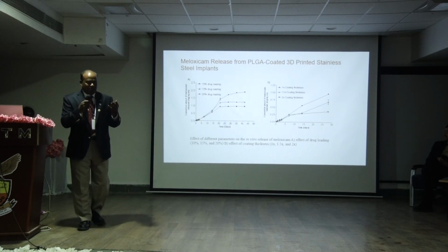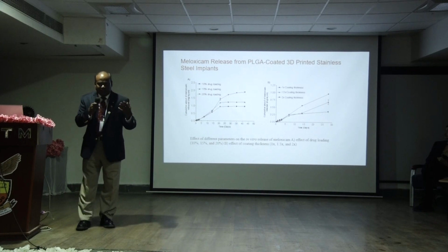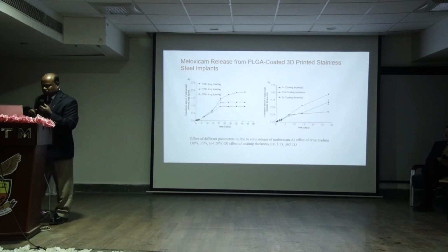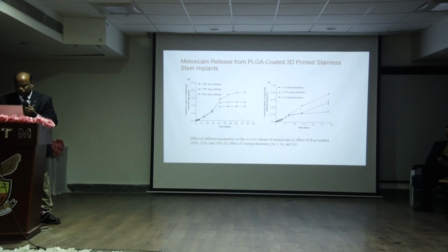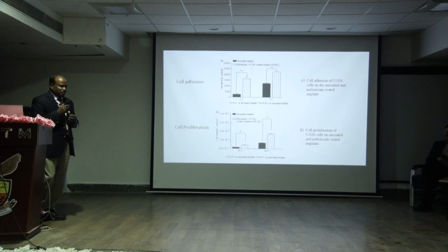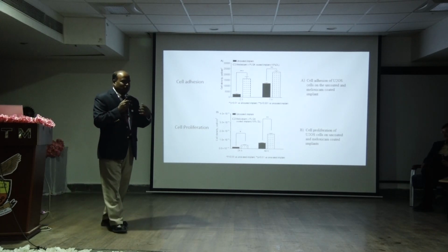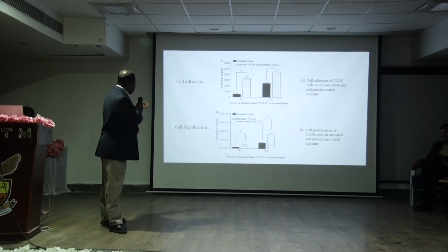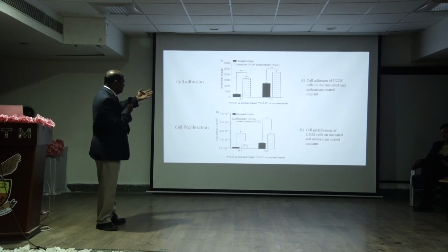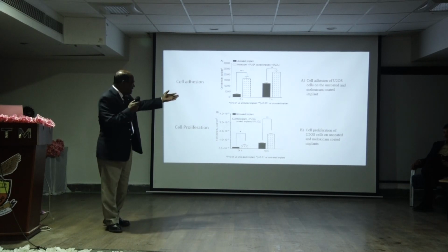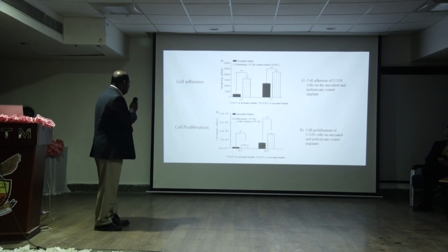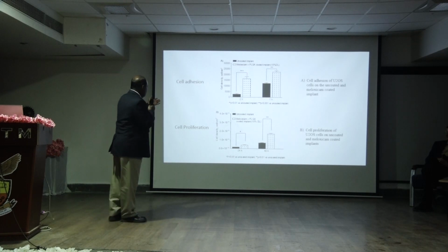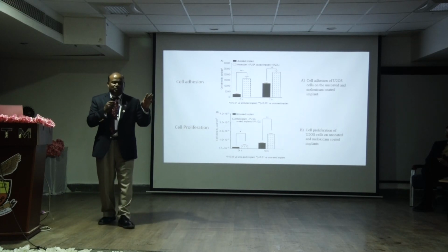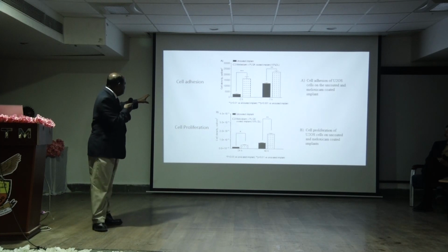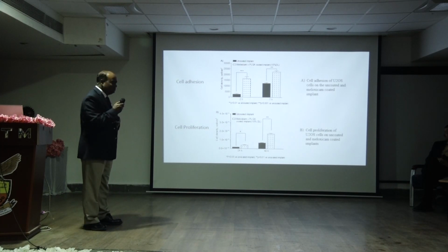By then, after the surgery, the wounds heal, and so the symptoms can be controlled. Inflammation symptoms can be controlled. So we did some in vitro assays to know what is going to be the fate of the implant in the body. We did some cell adhesion studies using osteoblastoma cell lines, U2OS cells, which are coated or uncoated. We use the blank uncoated as control, and then as you see that cell adhesion is promoted